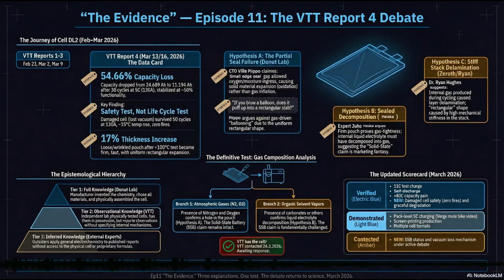But the most fascinating part of this VTT report isn't the final number, it's the shape of the capacity loss. The curve. Yeah, it wasn't a steady, gradual decline like you'd normally see. No, the degradation curve is the single most vital piece of diagnostic data we have. Paint a picture of it for us. When you chart it out, the capacity was perfectly stable for the first 6 cycles. It held strong. Like nothing was wrong. Right. Then, between cycle 12 and cycle 26, it experienced a rapid cliff-edge decline. The capacity just plummeted. Like it just fell off a table.